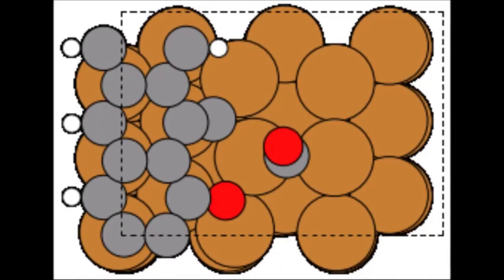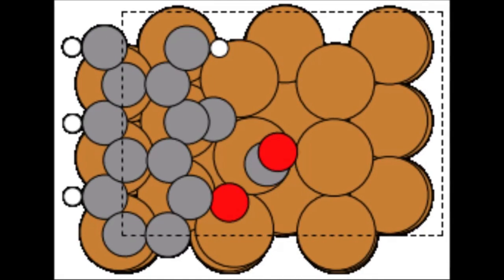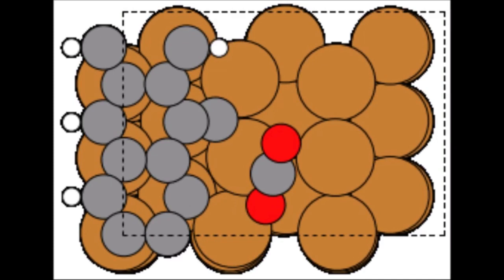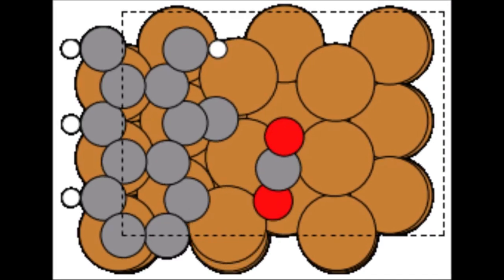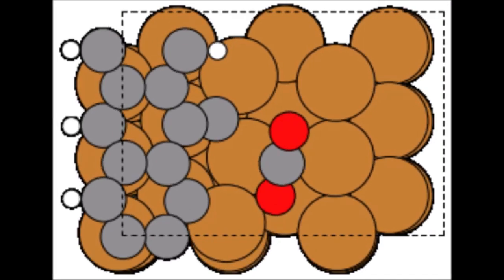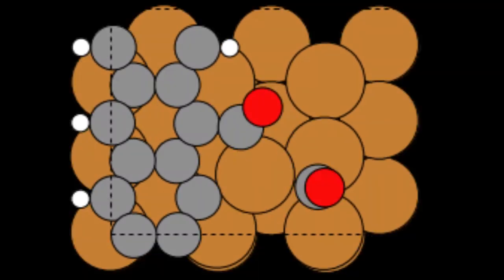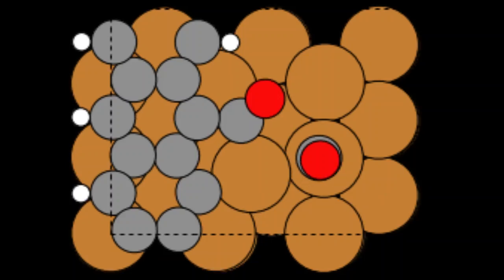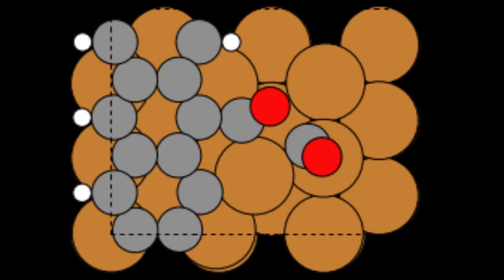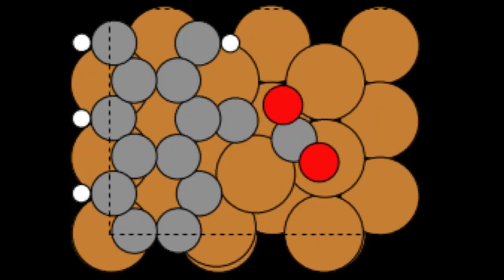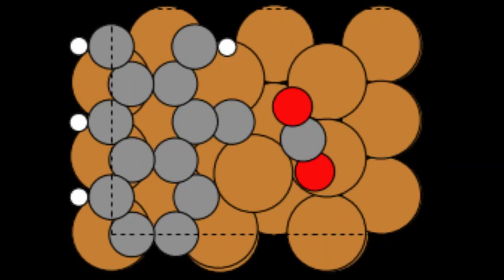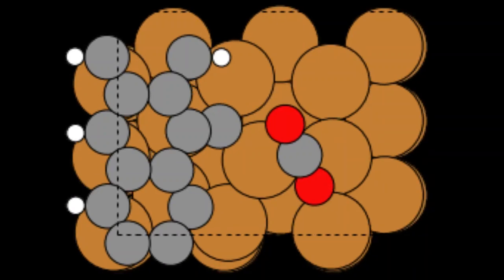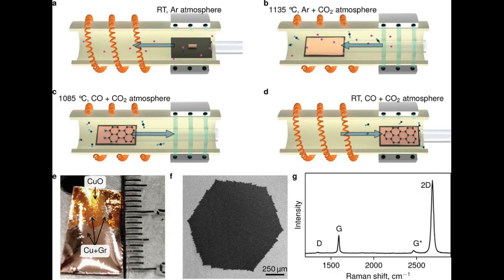Yet, once the first layer of crystalline carbon is deposited and separates the gas from the substrate, this tendency subsides. So, the process naturally favors the formation of a monolayer. Methane-based CVD can also operate in a self-limiting manner, but to a lesser extent. The researcher says that the system they used has a number of advantages. The resulting graphene is purer, grows faster, and forms better crystals.